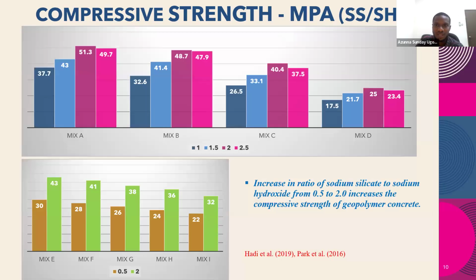That being said, another factor that affects the compressive strength is the ratio of the sodium silicate to the sodium hydroxide. I'm going to take some time to explain this a bit larger. You can see that here, for mix A, it kept going up. When the ratio is one, you have about 37.7 for mix A. So the ratio kept increasing up to a ratio of 2. But when you got to 2.5, you realize that it came down.